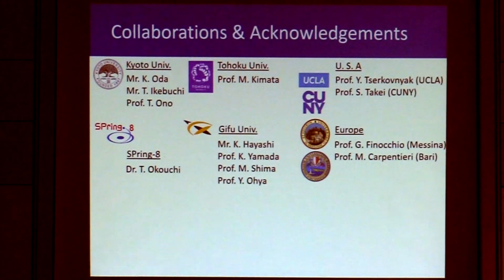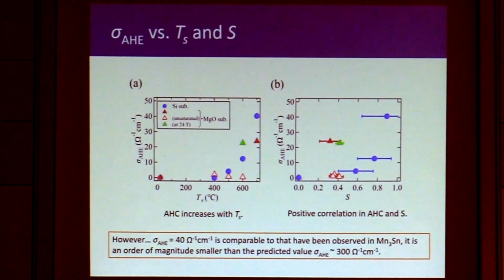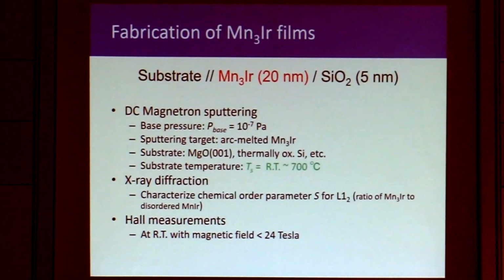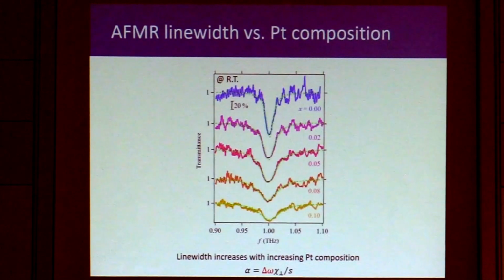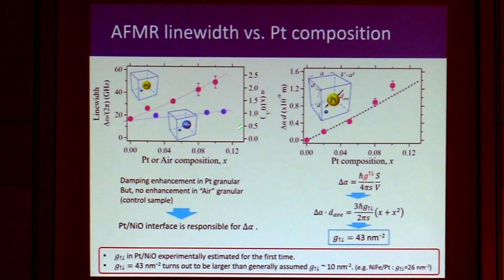So if it's a simple inhomogeneous damping, we may be just comparing this with the control sample, where you just create inhomogeneity without platinum in the nickel oxide. I mean, this air granular sample. You see an increase? Yeah, but a slight increase. I mean, it's a different disorder that we're using.